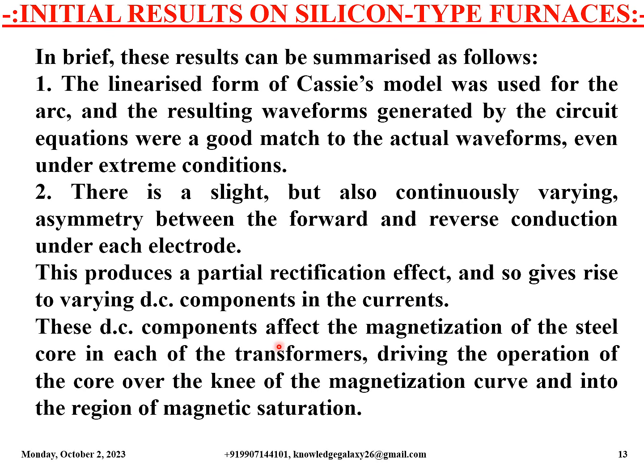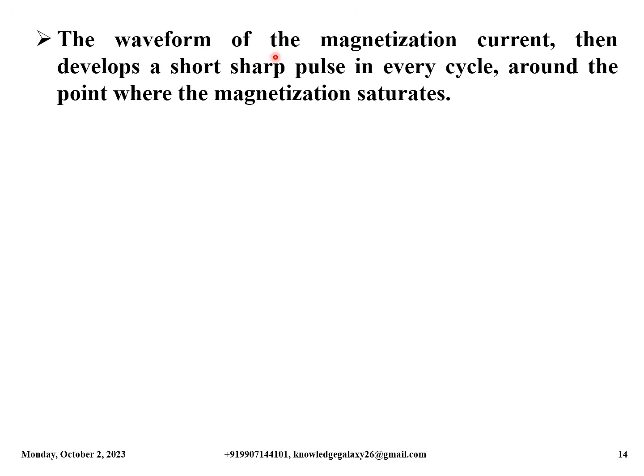These DC components affect the magnetization of the steel core in each of the transformers, driving the operation of the core over the knee of the magnetization curve and into the region of magnetic saturation. The waveform of the magnetization current then develops a short, sharp pulse in every cycle around the point where the magnetization saturates.